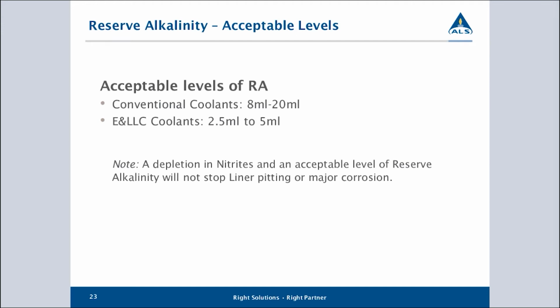Conventional coolants generally have higher RA than the newer hybrid or long life coolants, but essentially what you see on screen, 8 mils to 20 mils would be typical for an older style conventional coolant. 2.5 to 5 mil will be what you would see for the newer style coolants. In and of itself, it's just telling us what the coolant's ability is to absorb acid. It doesn't necessarily tell us the coolant's ability to stop corrosion. So you may still have a very acceptable reserve alkalinity, but if the inhibitor additive, say sodium nitrite, has been consumed, corrosion will still happen. The RA itself will not inhibit corrosion in the system.